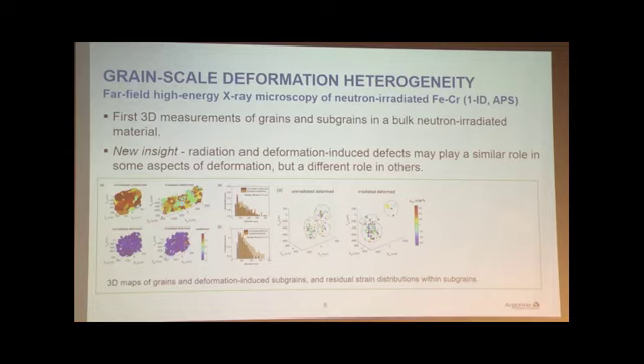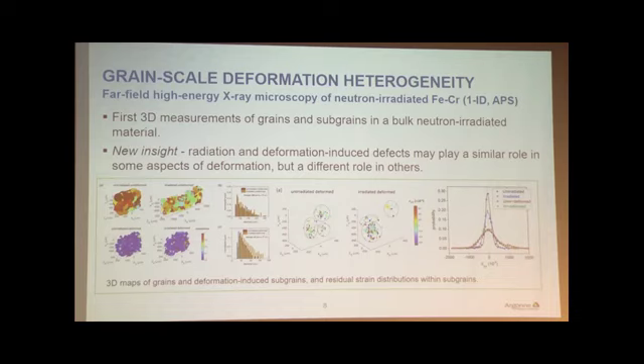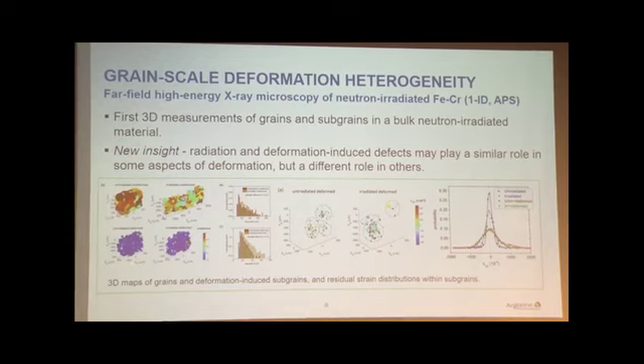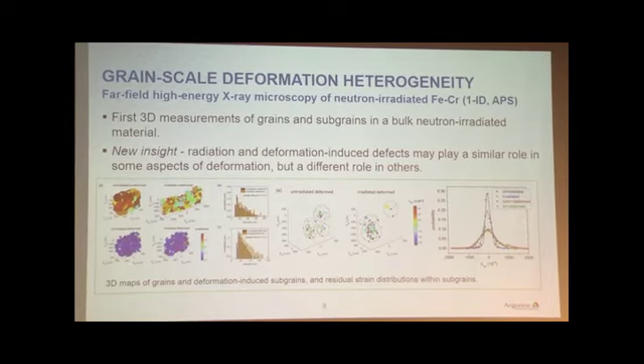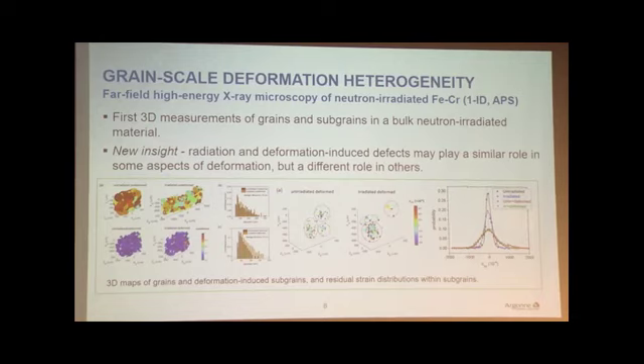So what you're seeing here is a neutron-irradiated iron chrome alloy. Before radiation, we can map the grain in 3D. And after radiation, when we map again, the grain didn't change. But during deformation, the grain actually split into subgrains. But if we compare the subgrain map between the non-irradiated sample and the irradiated sample, we do see a difference. In the irradiated sample, there are some large subgrains coexisting with small subgrains. But in the non-irradiated sample, you only see small subgrains. So what does that mean?